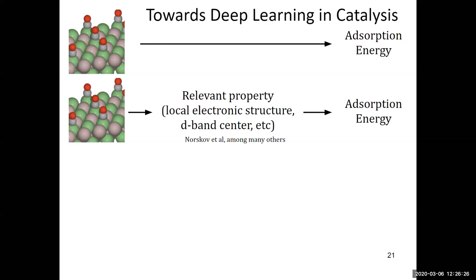This is awesome in that it tells you what's important. And it works really well for pure metals, where there's only one d-band center, and it's the same for all the elements. But this breaks down if you have bimetallics. And getting this thing requires a DFT calculation. So it doesn't really help us in screening a lot of materials. It's more on understanding what's happening.